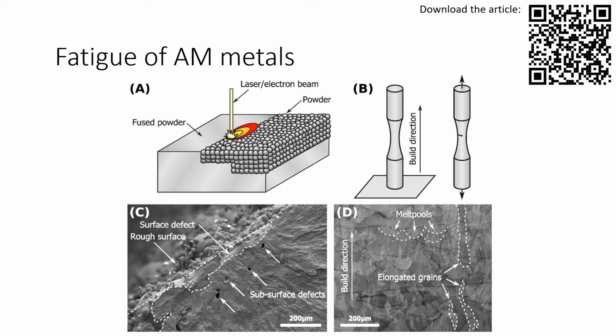We'll be using some notched Inconel samples prepared by additive manufacturing as examples. Okay, so with fatigue of additively manufactured metals, we typically manufacture something. Here I have the example of powder bed fusion, where powders are fused together by a laser or electron beam to form a component or a part. So what is typically done is a specimen is built and the specimen is tested, and what we typically see, as we see in C, is that we have a very high surface roughness, there are some defects, and in D we see some anisotropic microstructure, elongated grains.